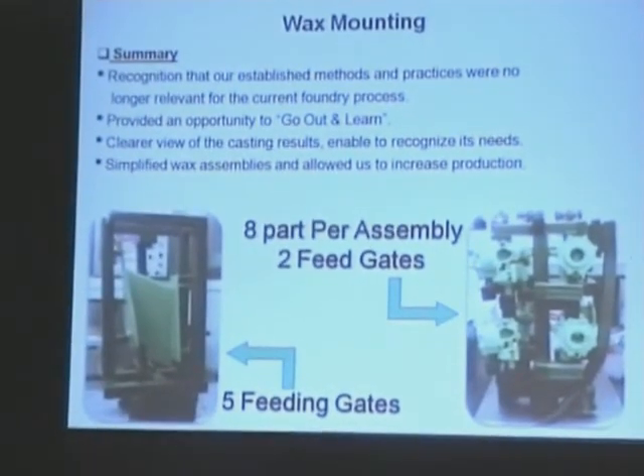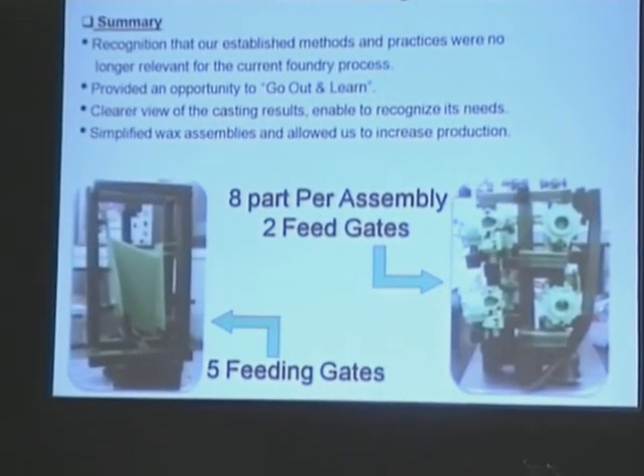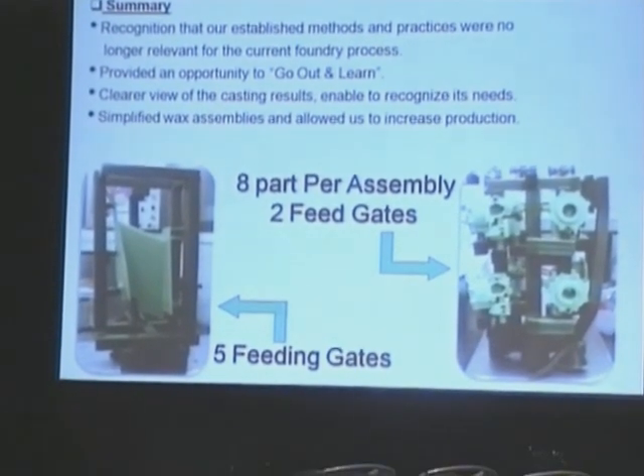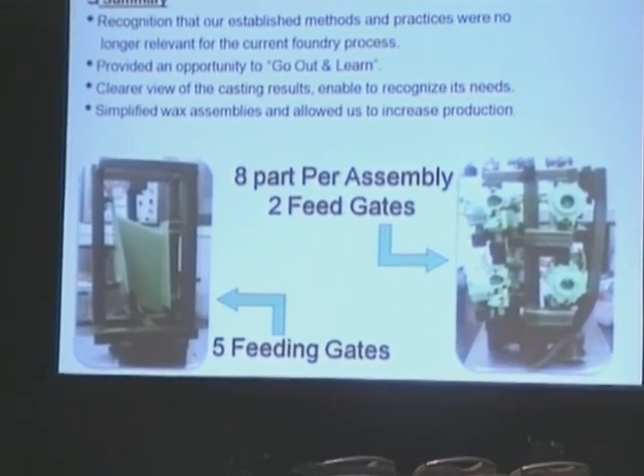So, recognition that our established method and practice were no longer relevant to our current foundry process, which maybe they were relevant back in the 70s or 80s when we had small parts. So it's a small part, put it in and get it over with. Now we have big parts, and you can't keep on doing that method. So, like we were saying, ring became 5 feeding gates, or those small valves became 8 parts per assembly instead of 4, with only 2 feed gates per part.